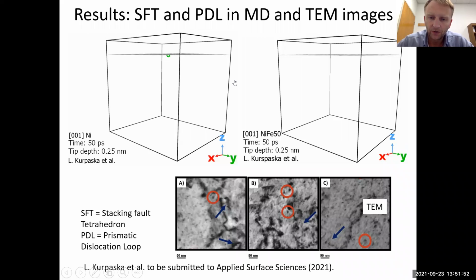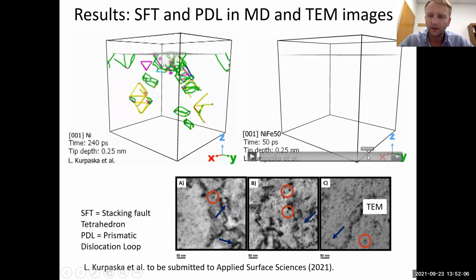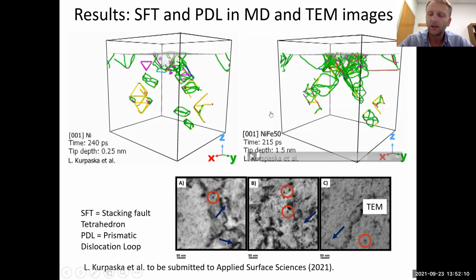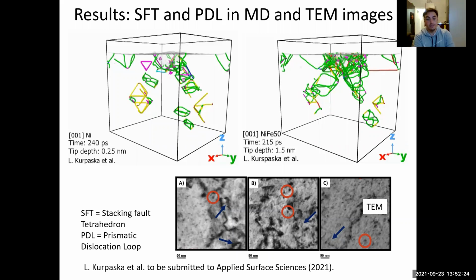What Javier said is that we see a very nice correlation between the amount of the defects generated and the size. You can see that figure C, which represents 50% iron, has more defects, but they are smaller in size. And this is exactly the same as what Javier got from his calculations on the dislocation density. But this is post-mortem analysis. Still, of course, we see that the stacking fault tetrahedra and prismatic dislocation loops coexist. But we are able to study a certain volume of the material. Okay, good. Thank you both very much indeed.